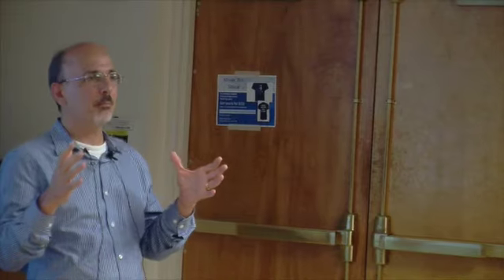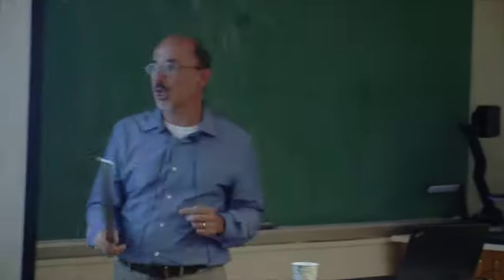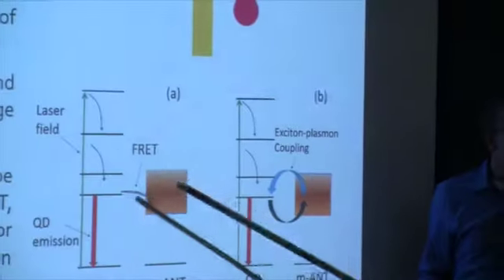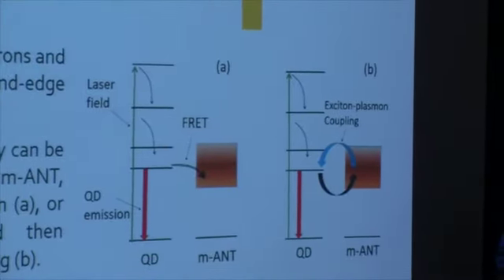So what happens is that if you have a nanorod, you have plasmon. If you have a quantum dot, you have exciton. And there is a lot of literature talking about how if you put them close to each other, they get coupled to each other. The coupling can even be so strong that it degenerates the state of the quantum dot. It generates plexcitons. There is a lot of theory behind that. But here I talk about the type of exciton-plasmon coupling where the plasmon is not generated by laser, but by the quantum dot.